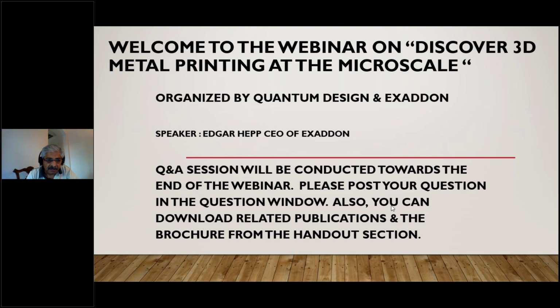Yeah. Can the system print oxide materials? Oxide materials, yeah, in a certain way we could. We don't want to, because when we generate hydrogen, there is a possibility that there is oxide inside, because the electrolytic bath we're using is water-based, and there is a possibility that it oxidizes right away by printing. But if you want to have smooth and straight surfaces, it's not something we want.